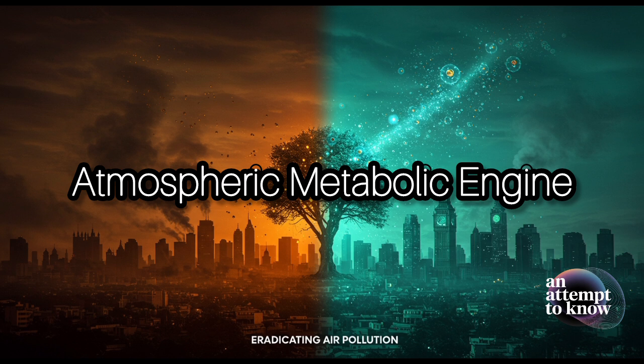That's a huge leap. And I read something fascinating. These nanofilters are put into 3D printed mycelium structures, fungus-based. Yeah, sounds wild, right? But mycelium, the root network of fungi, creates these incredibly versatile, sustainable, porous structures when 3D printed, perfect for embedding the filters. And the results? Pretty stunning. They're seeing 96.2% removal of PM0.1, those really tiny, dangerous particles. And they convert almost 90%, 89.7%, of NOx gases into ammonium nitrate fertilizer.